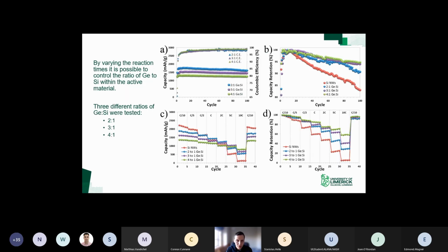When we cycled those, we got very stable capacity over 100 cycles for all three different materials. We looked at three different ratios: 2:1, 3:1, and 4:1 germanium to silicon. What we saw was the higher the germanium content, the lower the capacity, but the better the rate capability. The reason for that, as I said earlier, is that germanium has much higher conductivity than silicon, and also better lithium diffusion within it.